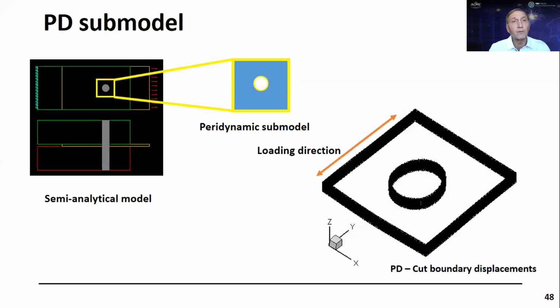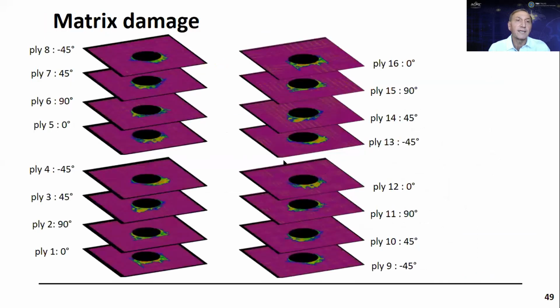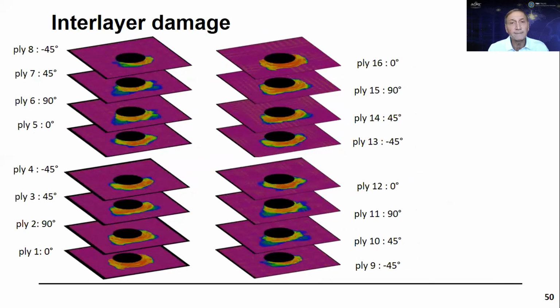In this case, we use Peridynamics as a submodeling tool. We have the semi-analytical model to determine the stress field and the displacement field. For the submodel, we have cut boundary displacements. We impose them as boundary conditions and determine the damage in each ply. So as you can see here, in each of these plies, we have the matrix damage. And if I superimpose them all, this is the matrix damage. And I have the interlayer damage here.